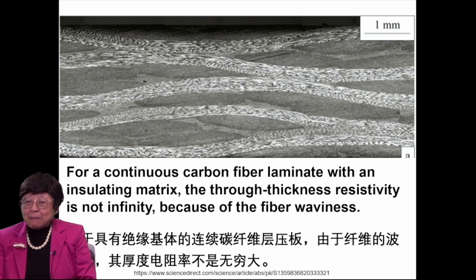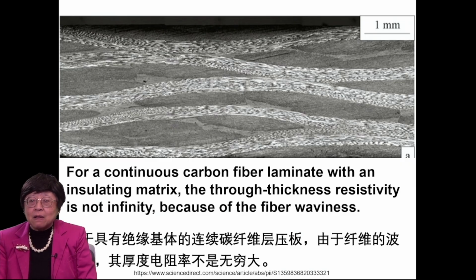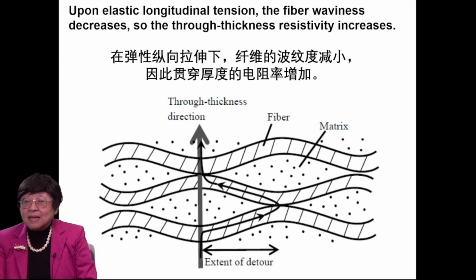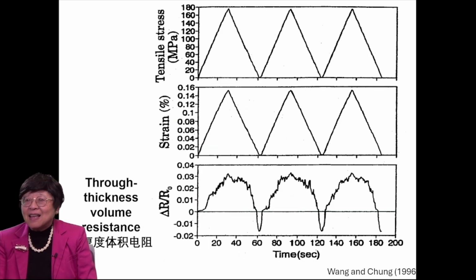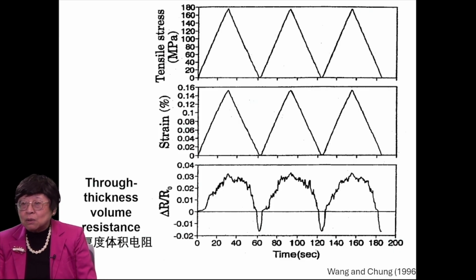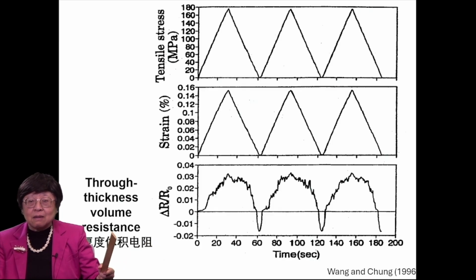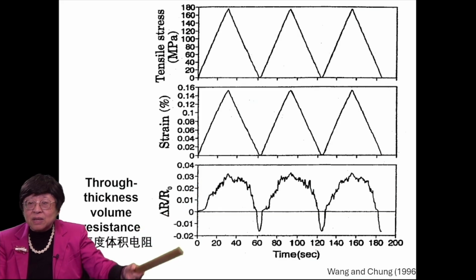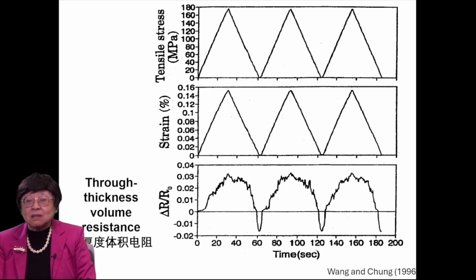Now, for a continuous carbon fiber laminate with an insulating matrix, such as epoxy, the through-thickness resistivity is never infinity, and that's because of fiber waviness, which causes a degree of fiber-fiber contact. So upon elastic longitudinal tension, that is horizontal tension, the fiber waviness would decrease. So the degree of fiber-fiber contact along the through-thickness direction would be reduced, so the through-thickness resistivity would increase. Therefore, upon horizontal or longitudinal tension, we can monitor the through-thickness resistance, and we find that it increases every time one tensions, because the fiber waviness is decreased, and it occurs reversibly.